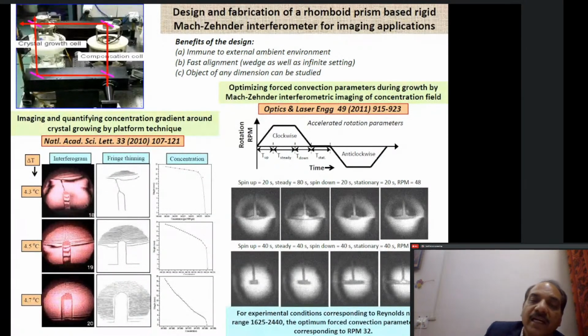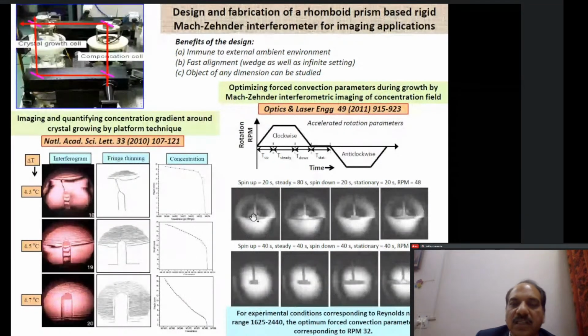And on the right hand side, you see there is another result, which is optimizing forced convection parameters during growth by Mach-Zehnder interferometry. What we did was we performed an experiment in which a KDP crystal was growing and it was continuously rotating, because when we are growing a crystal from solution, it is also rotated because we want to homogenize the solution from which it is growing. So in that case, basically we are adopting a forced convection regime.